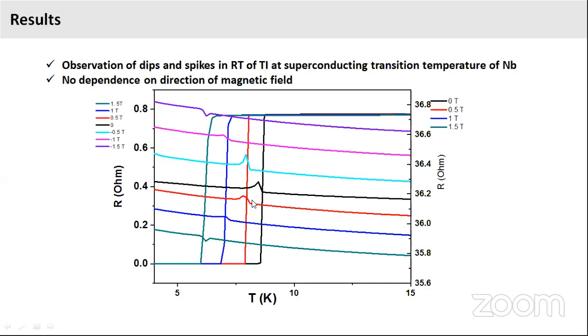And further, we notice that with increasing magnetic field in either direction, the spiking still exists and its position keeps shifting in correspondence with the superconducting transition temperature of niobium. But there is also a decrease in the amplitude of this spiking. And then very interestingly, at around 1.5 Tesla, there is an inversion of this spiking where the spike becomes a dip. And this happens in both magnetic field directions. So this result, where the magnetic field strength introduces some kind of a sudden change at a particular field strength in the induced superconducting property, is what made us try to explain this based on Pablo Burset's paper.